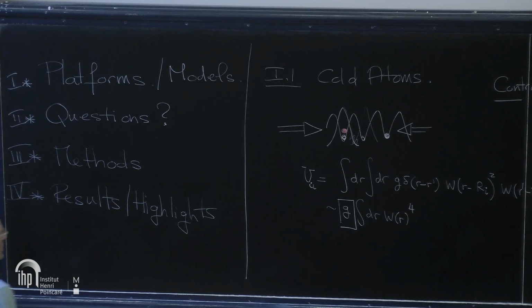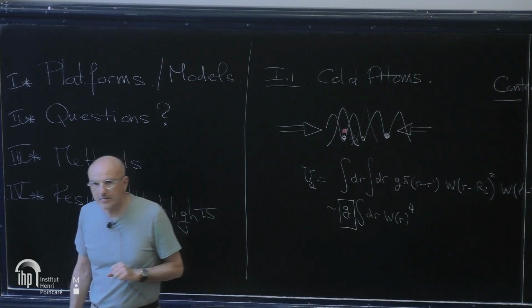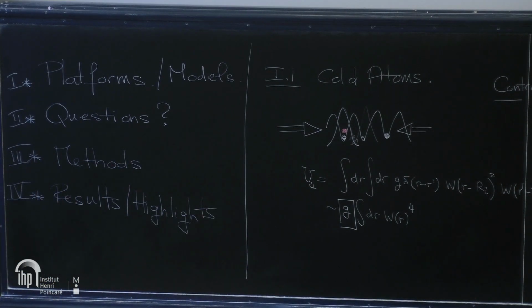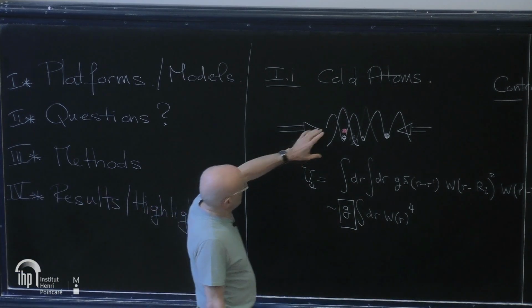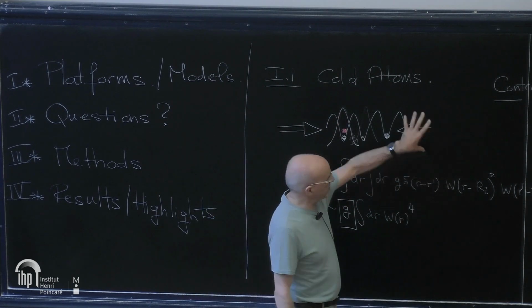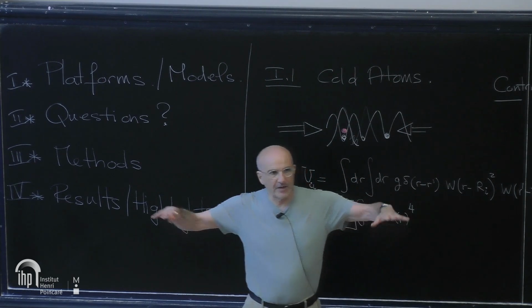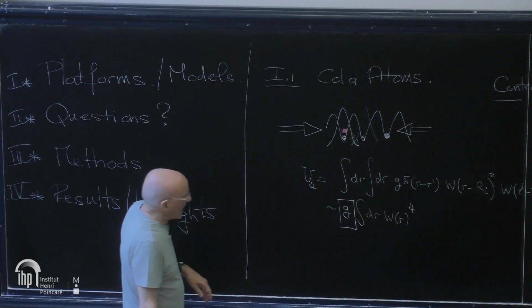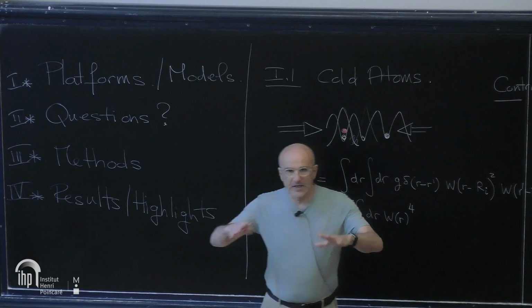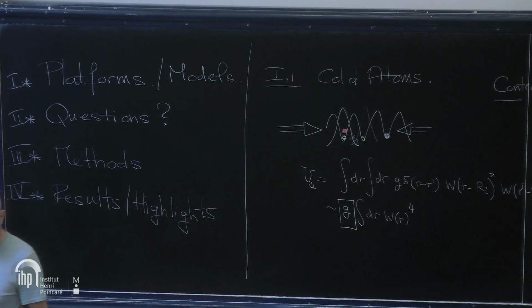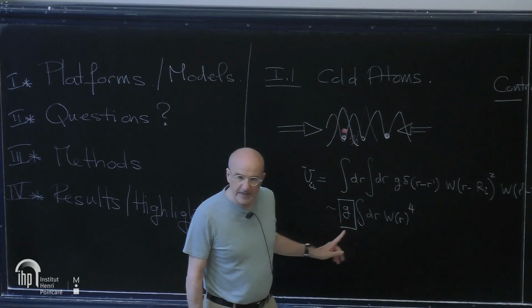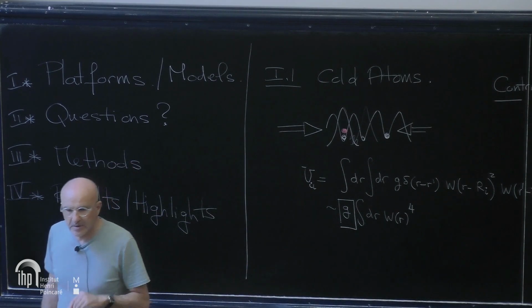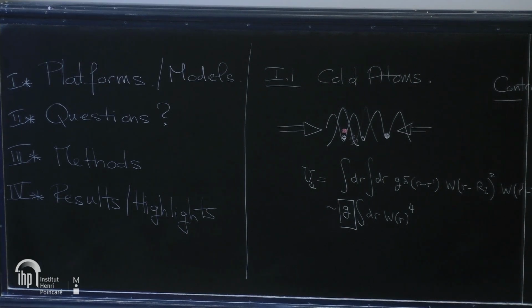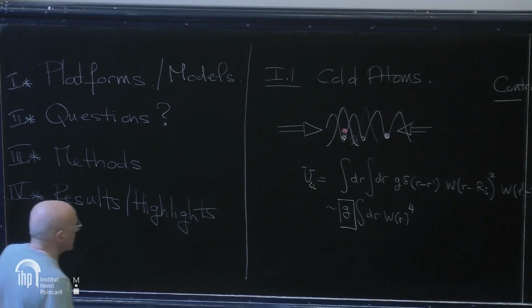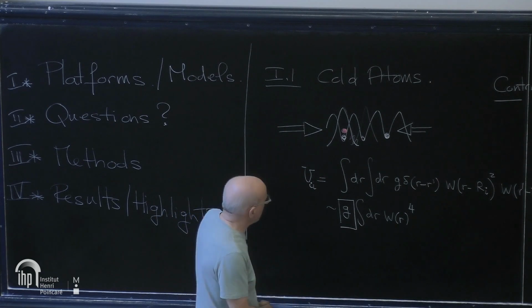or the amplitude of this periodic potential, which can be tuned even more easily by just changing the power of the lasers. So the power of the lasers will control the depth of this optical lattice. I can have a very shallow lattice or a very deep lattice. And hence, this will control the spatial extent of these Wannier functions, which also enter this expression. So you see that this interaction strength is tunable in two ways, both by controlling the power of the lasers and, in principle, by controlling the Feshbach resonance, if you can do that in the presence of the lattice.